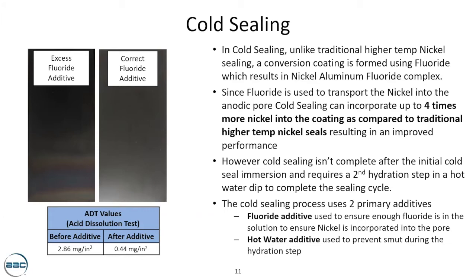Now, if you look in the pictures here, the fluoride, as I mentioned, is a key element to this. And if you don't manage the fluoride correctly, one of two things can happen. If there's not enough fluoride, you won't get a good seal and you'll get a poor ADT value.